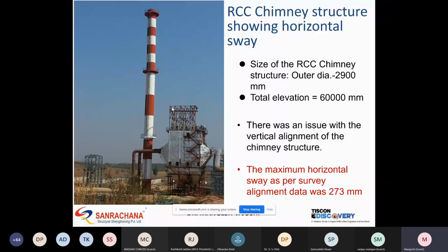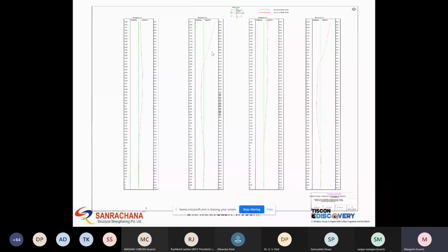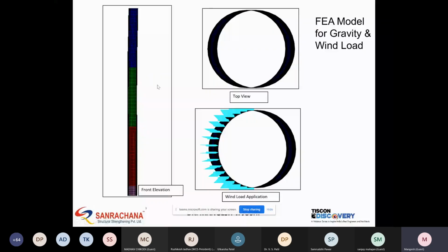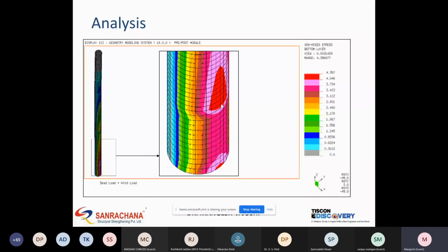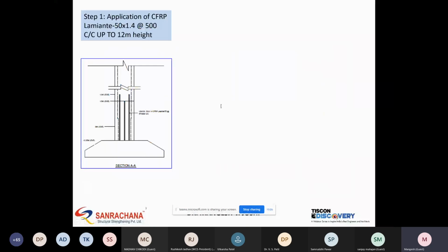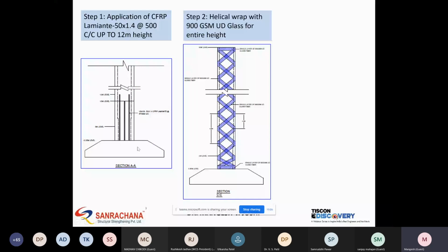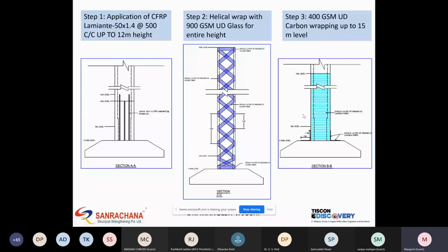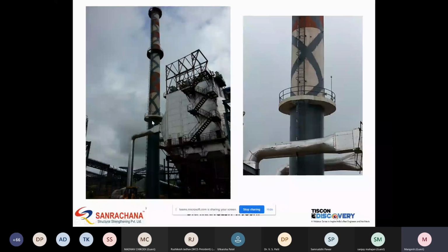Because of that eccentricity, for modeling, we need to first find out the eccentricity in all quadrants. So we carried out a total station survey, and through it we found out the eccentricity in all the quadrants. Based on that, we modeled it with FEM with that eccentricity, because otherwise this chimney would have been a simple axisymmetric problem. But this inclination made it a bit complex. So with this inclined nature, and after putting wind load on it, we found out the additional stresses coming at the base, and the additional tension coming at the base because of this eccentricity. Then we provided carbon laminates at the bottom and this helical wrap, and at the bottom again we wrapped with 0-degree orientation. So these are the photographs you can see. This is the entire chimney. From the bottom we provided carbon laminate followed by wrapping, and at the top we provided these helical wraps.